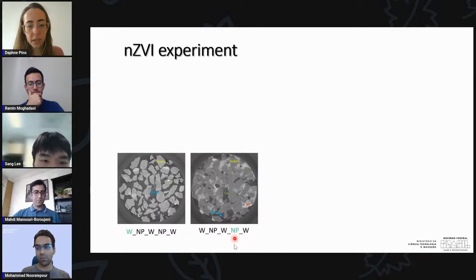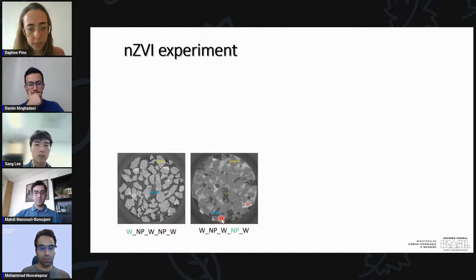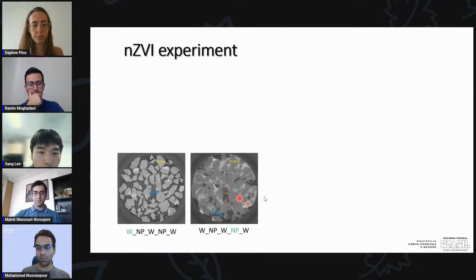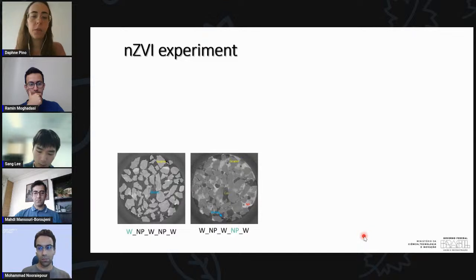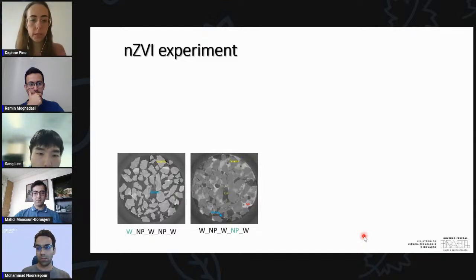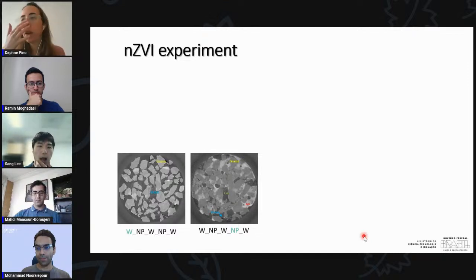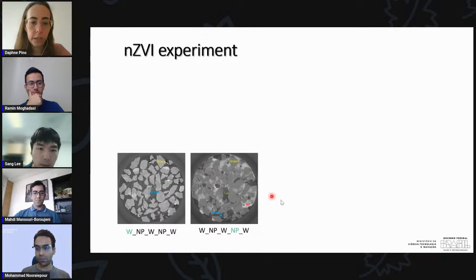After the second nanoparticle injection you can see grains, water, and nanoparticles in a brighter gray, along with some gas bubbles that formed. This is the kind of image we get from our detector. We then segment the image — separating those phases — so we can calculate volumes, surface area, and essentially anything you can think of. We can also perform permeability calculations once we have the porosity data for each injection phase.